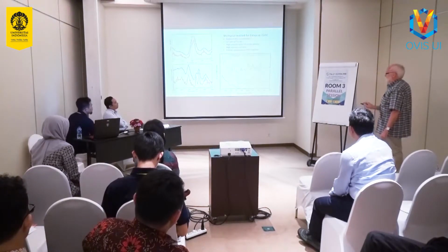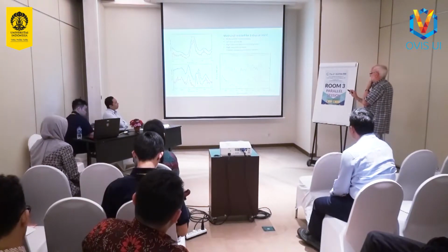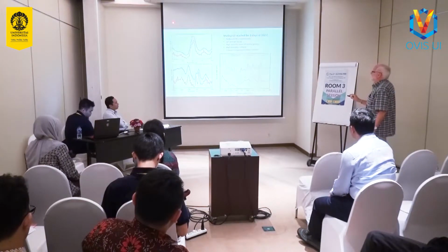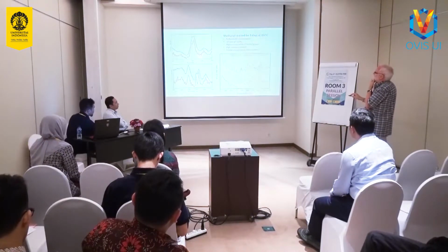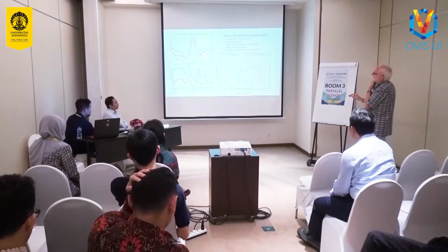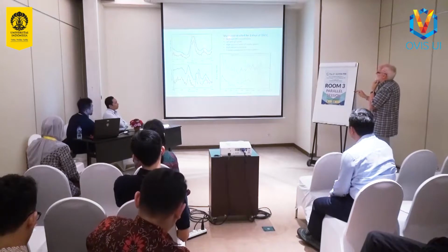Well, in the reactor we can stop after 3 days and we can stick it into the neutron source and see what's there. That's what we did. So, again, these spectra have been recorded on different instruments, so you can see different frequency ranges being displayed and different resolutions depending on what instrument was used. But look at the high frequency end first, 2 different instruments. We're still seeing some hydroxyl groups from the zeolite. Not a sharp band like you see in the infrared because of the poor resolution, but this is the residual OH groups.